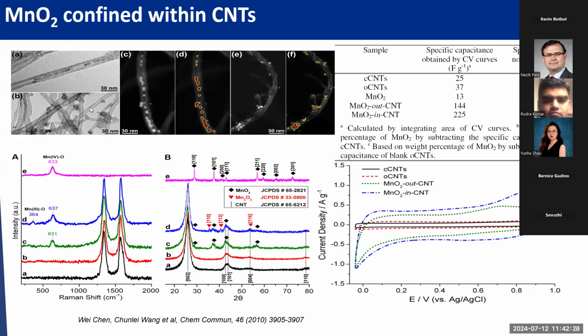So we made two types of composites. One is manganese oxide confined inside the nanotube. Another is manganese oxide particles just deposited outside the nanotube. So we compare these two composites. We also have a control sample, basically the closed tips carbon nanotube. That's the commercial product. Then we can also open the tips of carbon nanotubes. The goal is after you open both tips, you can put the manganese oxide precursor inside the carbon nanotube. Then you can do the decomposition, then create this manganese oxide inside the carbon nanotube composite.